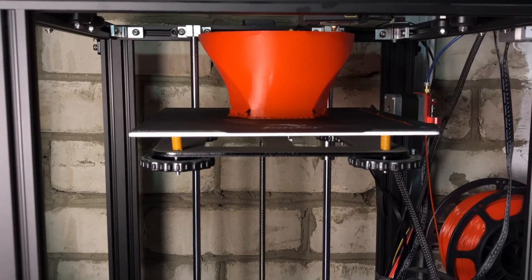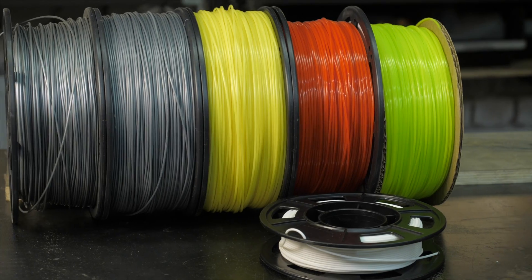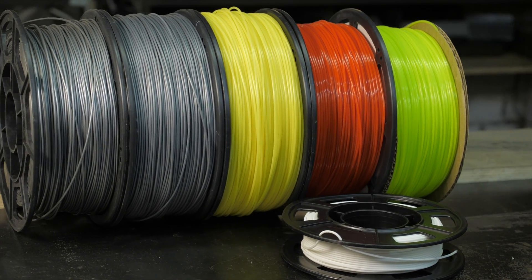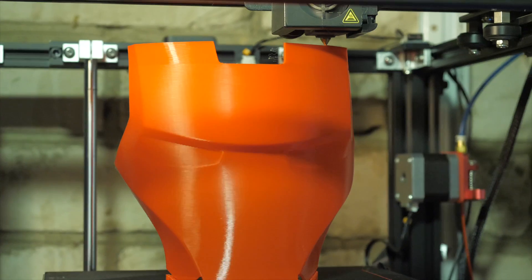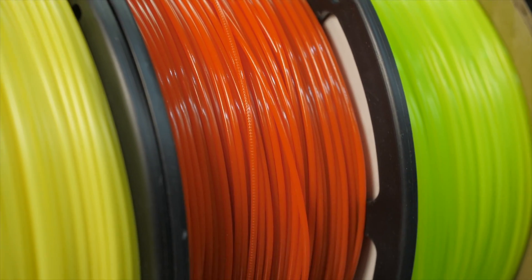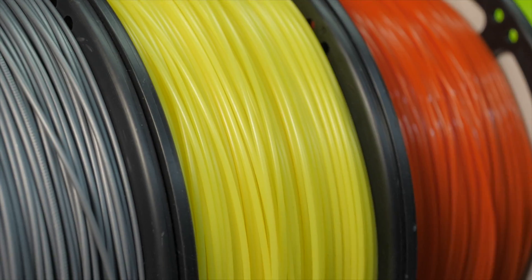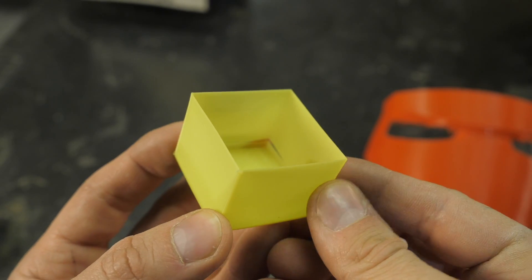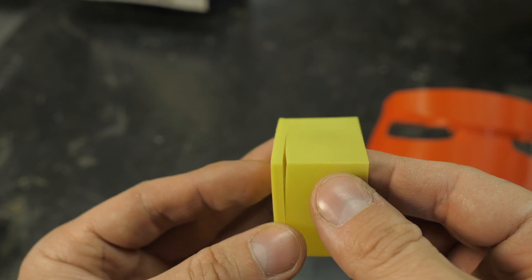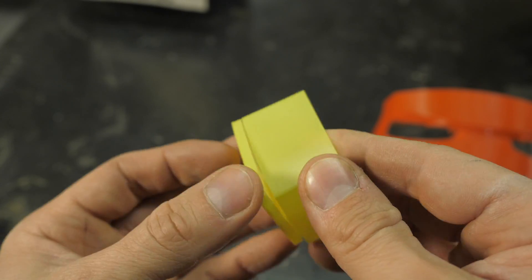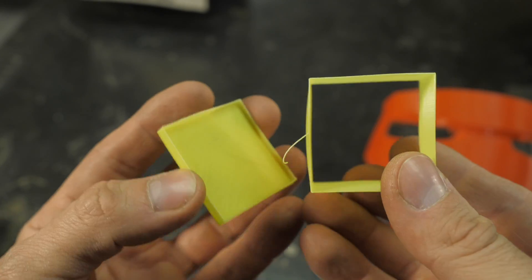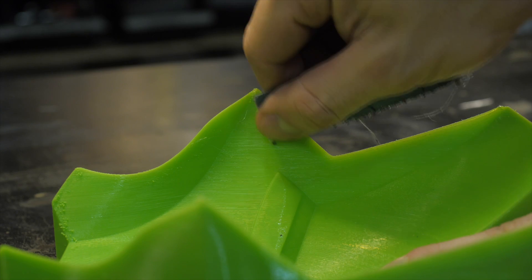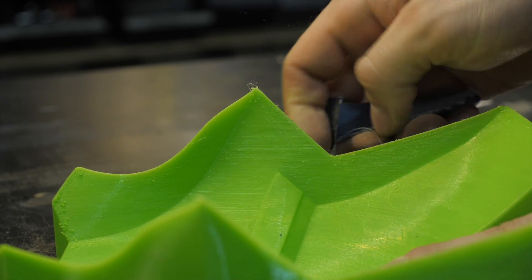A 1 mm nozzle allows you to print with a layer height up to 0.5 mm and get light and strong parts many times faster. Printing this mask, for example, took a little over 1 hour. So far, based on tests with different materials, I have come to conclusion that it is better to use PLA for printing large single layer parts. Originally, I wanted to use ABS because it is more resilient than PLA and easier to sand. But internal shrinkage and delamination of ABS plastic during cooling becomes too critical when printing with 1 mm nozzle in one layer. PETG doesn't behave as well in further processing as PLA.